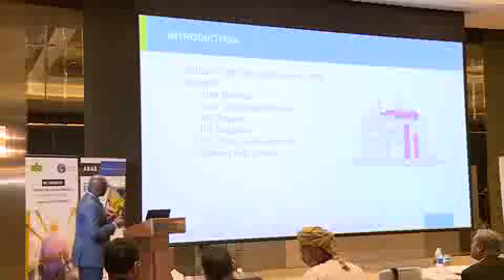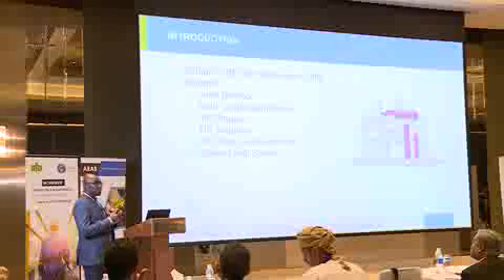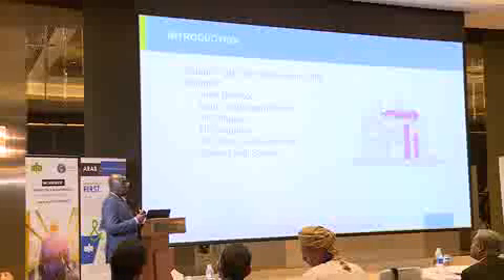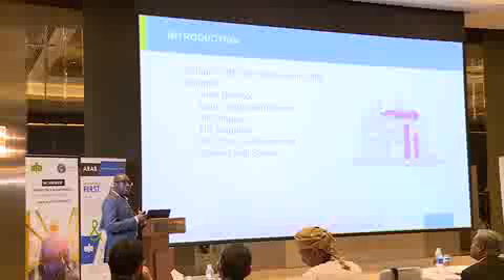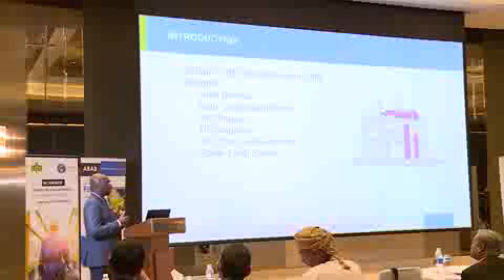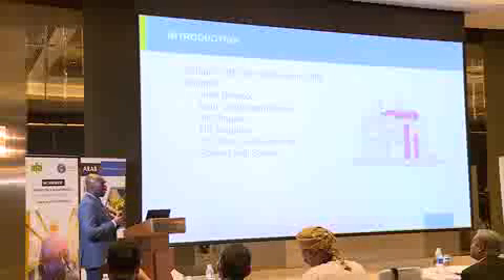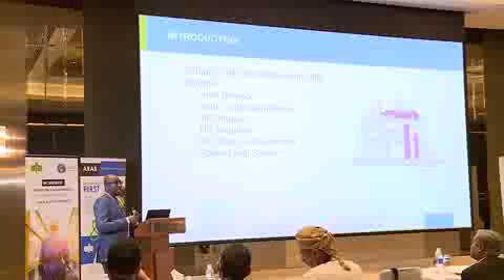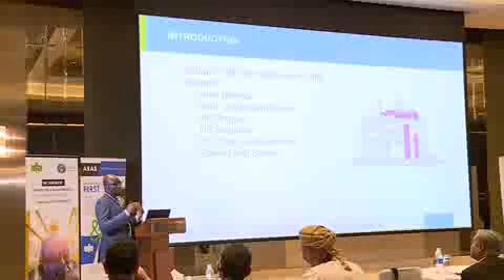And at that time, they teamed up together again with Sandvik to come up with a material, and there were a few goals. So first of all, this material should be better in corrosion resistance than the austenitic materials. Secondly, the weldability should also be good. They also looked at mechanical properties. And then the last point was they would prefer it if the material can perform in less oxygen or actually zero oxygen.